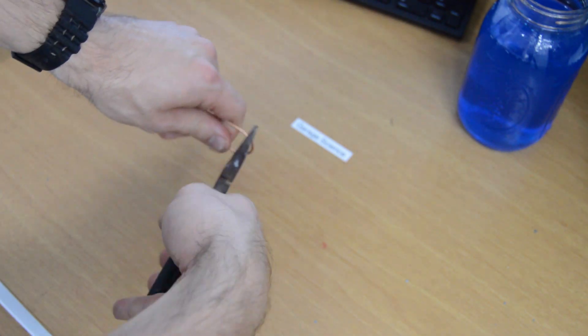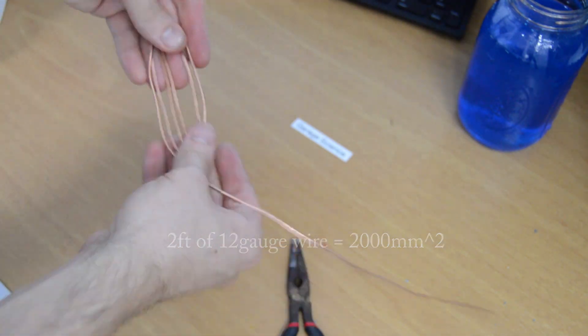Take some copper wire and form it into an electrode similar to mine. I've bent the top so that it will curve around the inside of the neck of the mason jar. Your copper electrode should have about a 2 to 1 ratio with your part that's going to be plated. I did not do this and used a ratio closer to about 4 to 1, and you'll see that my solution progressively gets more and more green as more copper is dissolved.